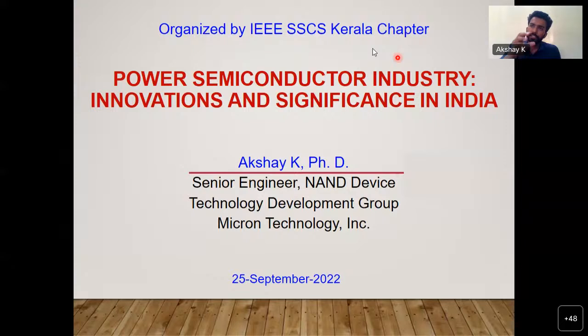Coming to GaN, it is going to have a big play in the below 1.2 kV market, around 600, 700 V, for, let's say, electric vehicle chargers, which would need somewhere around 600 to 800 V. For those applications, GaN definitely will have something. And for RF applications, of course, because GaN has very high mobility, it can switch extremely fast. In all those applications, GaN will definitely have its own advantage, where silicon carbide doesn't have that kind of high mobility as compared to GaN. So silicon carbide is not good for RF applications and so on. There, GaN is definitely going to be the thing. But for very high voltage markets, silicon carbide is a much stronger contender as of now, unless GaN on GaN, like pure GaN substrates, are available at an affordable rate for the industry.